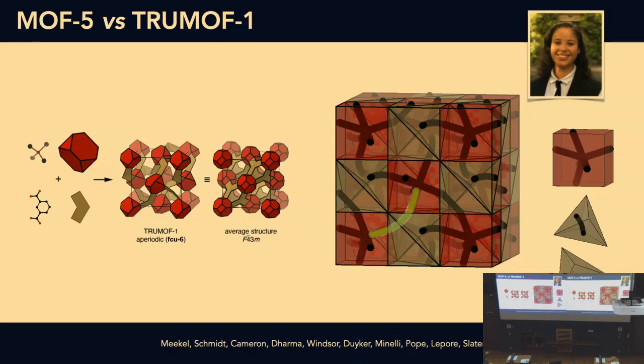And likewise, on the sites where the linkers are positioned, well, actually, in this structure, the linker doesn't have the threefold. Here's what that polyhedron looks like. It's a trigonal bipyramid, so it has threefold symmetry, but the linker doesn't have that. So when it's sat on the site, the connectivity breaks that symmetry. And in fact, to get the stoichiometry right, you have to have some sites that are actually entirely vacant. So now when you take these blocks and put them together and make everything match up, these are the Truchet tiles. There's an infinite number of ways of having these all match up, and every time you do it, you'll get something different, okay?